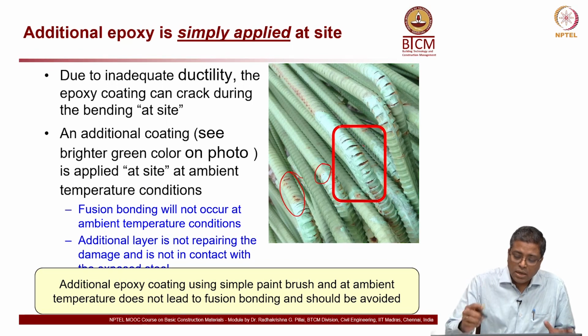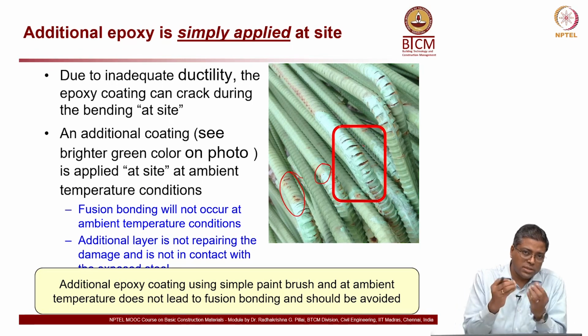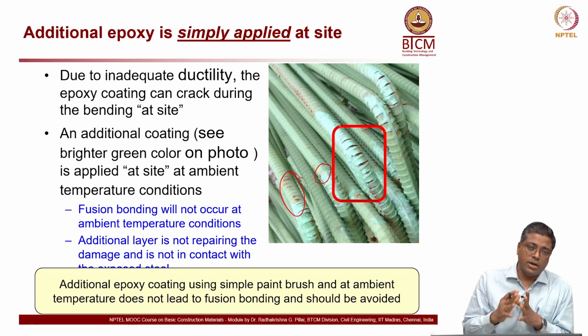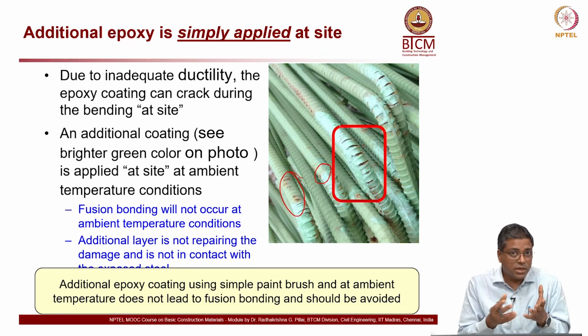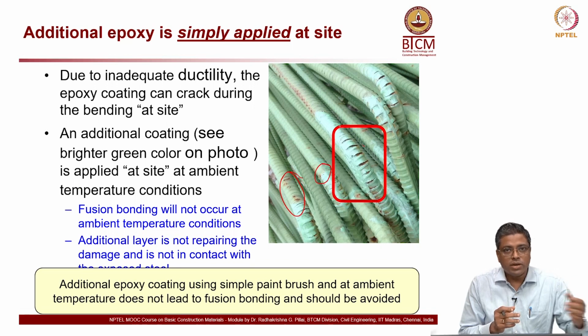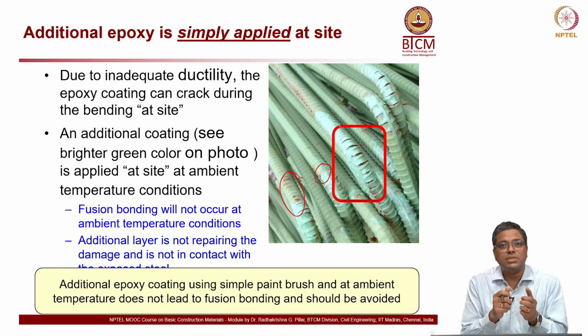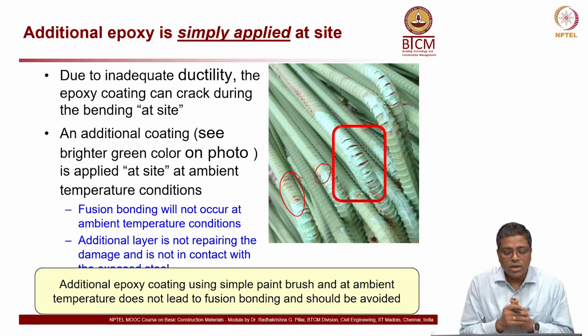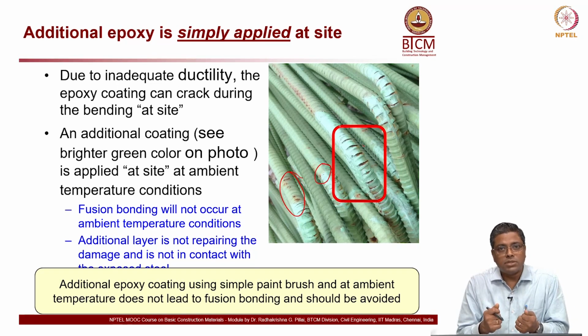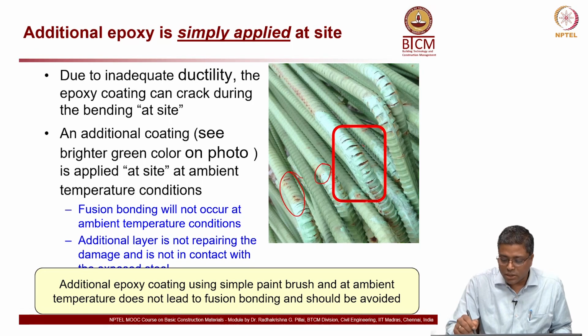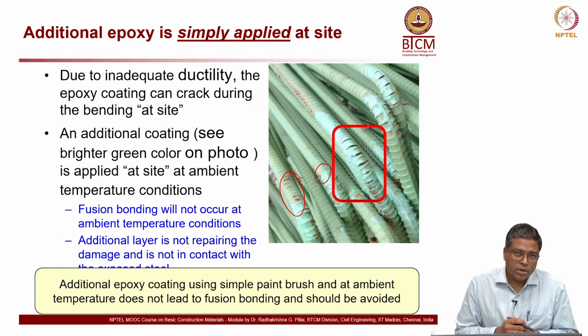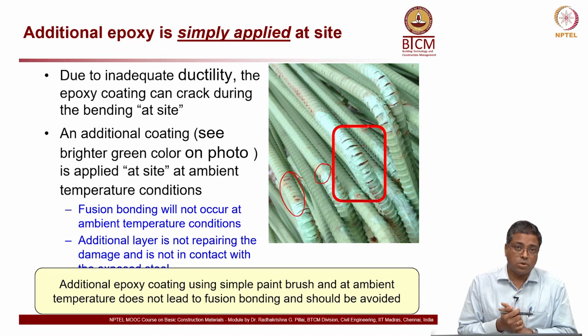And also when you expose these rebars at a construction site for a long period of time, what will happen is that the volatile materials in the epoxy, it's essentially a chemical, right? So when it is exposed to sunlight, it will become brittle. At home also you might see, if you leave plastic outside for a few months, you will see that it will start becoming brittle and deteriorate. A similar thing happens to this epoxy also. And now if you bend a bar which has a brittle epoxy, it will crack. So that's what is shown in this red rectangle there, where you have a cracked epoxy. This also will lead to crevice or underfilm corrosion.